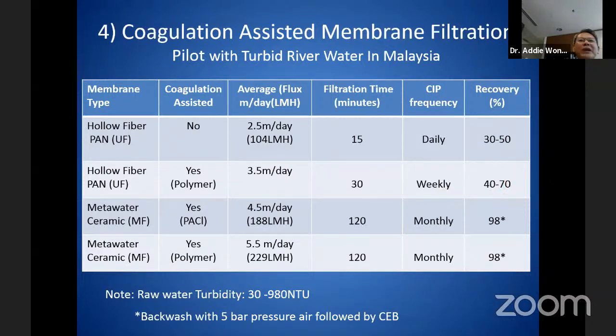So for the ceramic membrane later, if we put in PACl, we got 4.5 meters per day or 188 LMH, liters per square meter per hour, the flow. No? The flux, sorry. For those who are not familiar with membranes, the flux is the flow passing through the surface of the membrane per square meter per hour. So that's called flux, right?